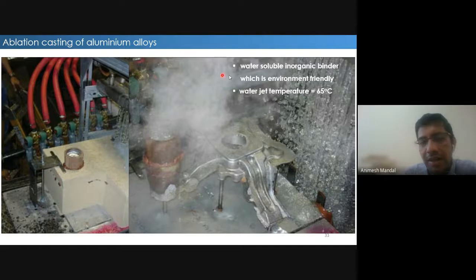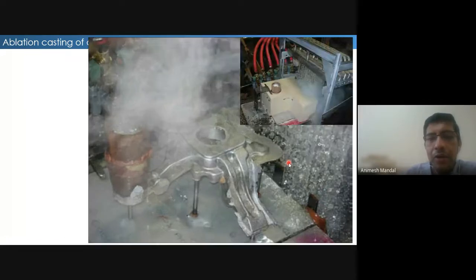The trick, or I'll say the secret, is designing an inorganic binder which is soluble in water, so that as solidification proceeds and you start this jet of water, immediately your sand gets ablated, due to this jet of water, which is generally kept at 65 degrees centigrade. As a result, you achieve an extremely high cooling rate in this modified version of sand casting.